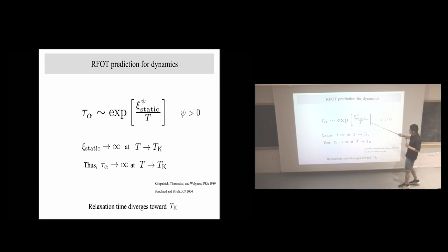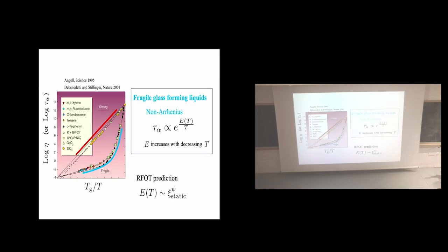Okay, so the RFOT gives you a prediction that, as you can see, this effective energy scales with basically the size of the static correlation length with some power of psi. So when I saw this prediction, I was very happy and quite excited. But according to recent work by Camille, it's not simple. And I want to pass this next to you.